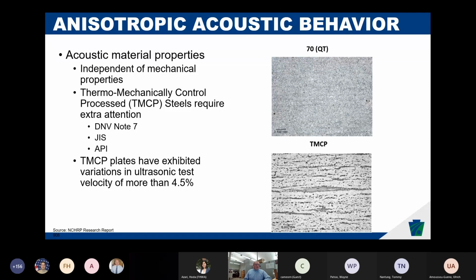You can see on the right these two microscopic images of different steels, grade 70 quenched and tempered, and a grade 70 HPS thermomechanically controlled process steel. It's been somewhat historically known that these thermomechanically controlled process steels have this anisotropic acoustic behavior to it. There's no issues with the mechanical behavior. Actually, this TMC process is used to get better mechanical properties. But throughout the globe, Norwegian shipbuilding spec here, DNV Note 7 addresses the need to consider TMCP for anisotropic behavior. So does the Japanese code and the API.